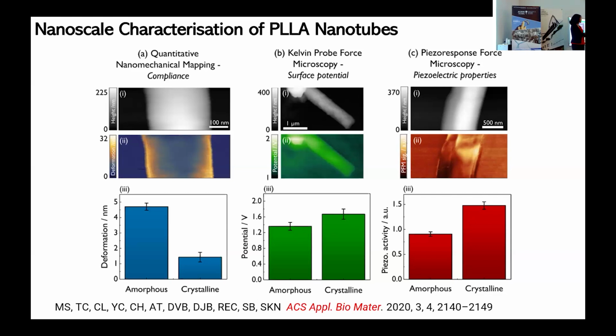We know that cells respond to the mechanical environment, to the cues that they get from, for instance, the stiffness of the substrate that they're on. So we believe that this is playing a part. But that's not all. There's also a difference in the surface potential. There is an electrical effect going on as well, where the crystalline nanowires have a slightly elevated surface potential. And finally, if you look at the piezoelectric response, here too, the crystalline nanowires have a higher piezoelectric response. So we believe it's a combination. It's actually the electromechanical environment that is having an effect on cell behavior.